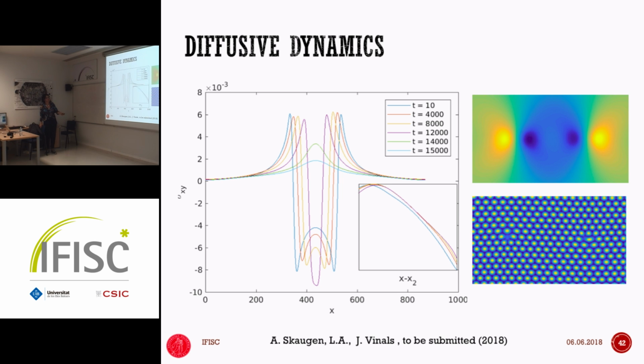That means we introduce a vortex in each of those phases, and we use the isotropic vortex approximation. That means that at the beginning, there is some sort of scaling law in the tail here that comes from whatever approximation we use for the vortex. We know that the flow field away from a vortex goes as 1 over the distance, right? So the stress is going to be like 1 over r away from the vortex. So that's what we're going to see here too. But as a function of time, we see that this power law tail disappears. We have crossing between the lines. So the self-similarity that we put in as an initial condition is not preserved by the model. And that's because the system is dissipative and it's not consistent with mechanical equilibrium.